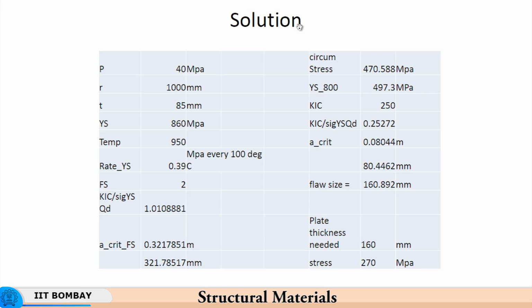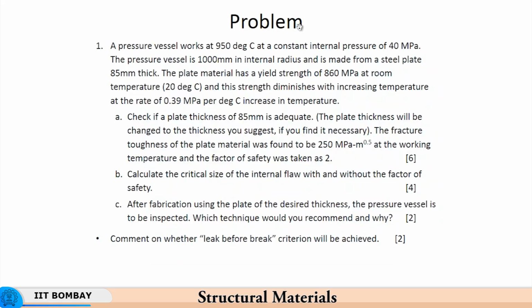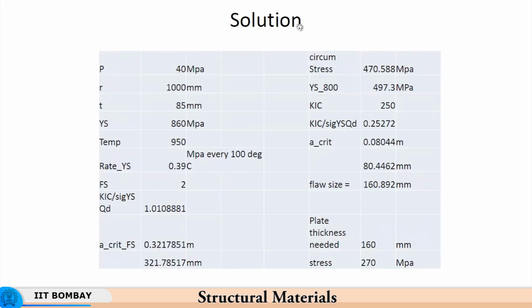Now, the yield strength is 497.3 MPa based on the fact that it is 860 MPa at room temperature and it degrades at a constant rate of 0.39 MPa per degree centigrade, actually. Just a minute, here it is per degree increase in temperature, at the rate of 0.39 MPa per degree increase in temperature. So, every 100 degrees centigrade it will change by 39 MPa.